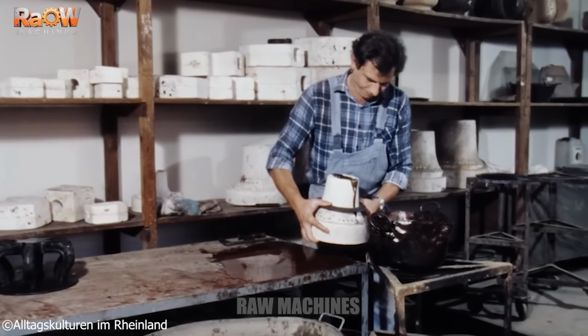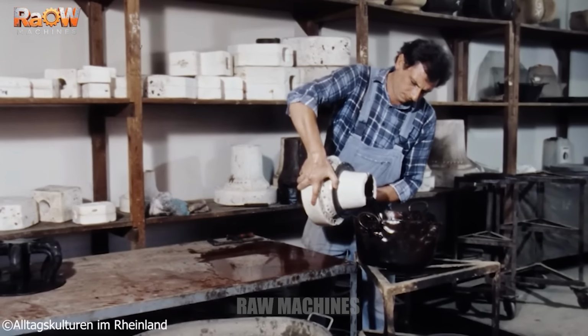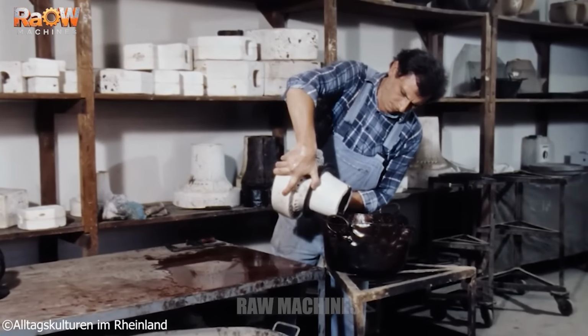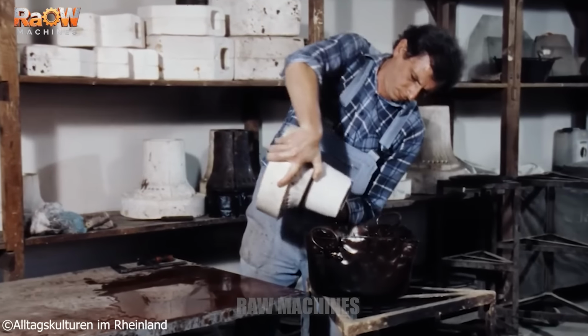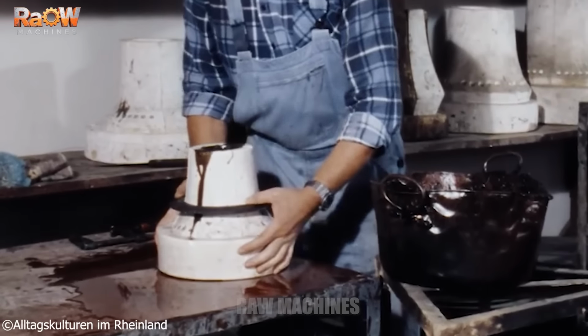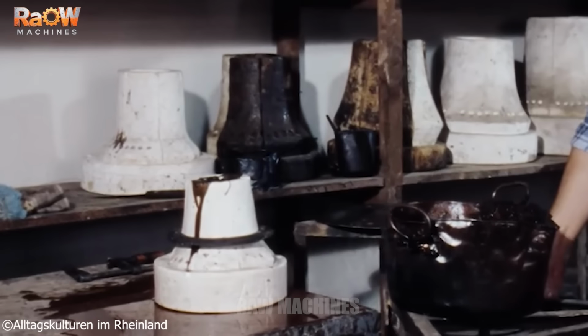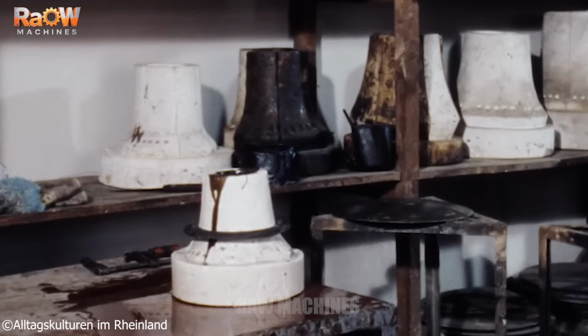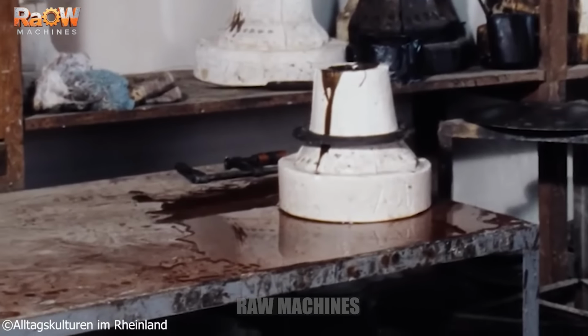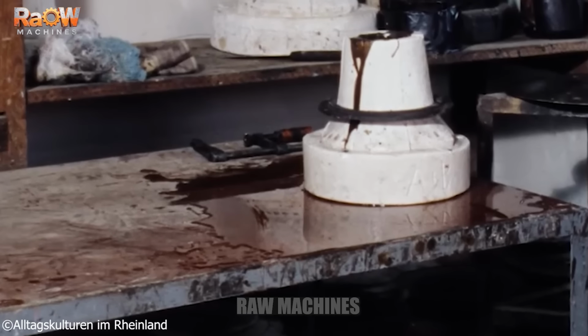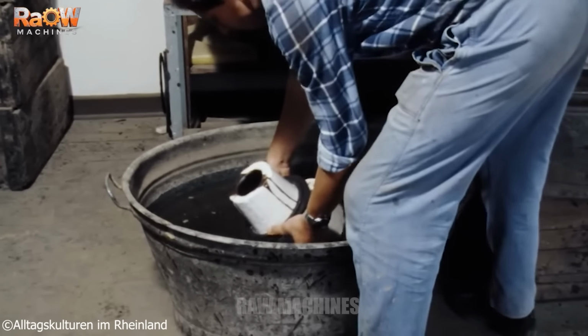The plaster models are submerged in water overnight to cool them thoroughly. Mold maker Wisław Sokolowski then heats specialized casting wax and pours it into the molds. Upon contact with the cold plaster surface, the wax solidifies into a shell, while the remaining liquid wax is poured out, forming a hollow wax model of the crown.